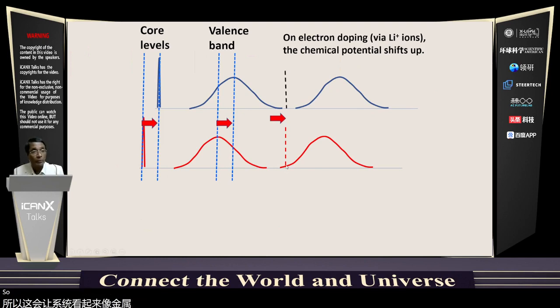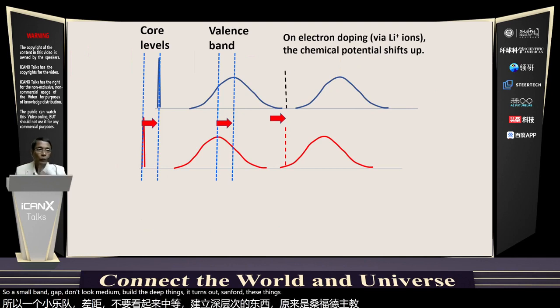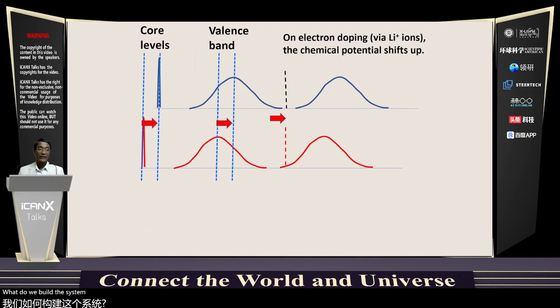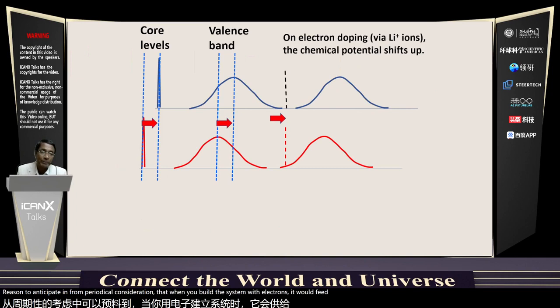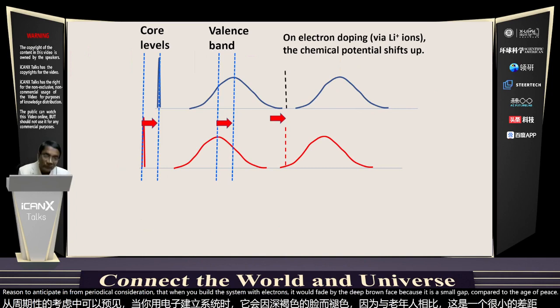So small band gap doped with lithium, doped with defects. It turns out sulfur defects also will dope the system with electrons. And there's a good reason to anticipate from theoretical consideration that when you dope the system with electrons, it will favor the T prime phase because it has a small gap compared to the H phase. So there's an energetic reason.